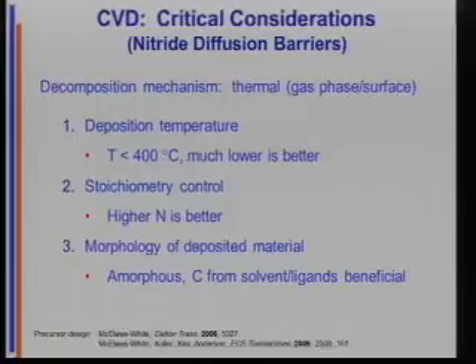So if we're talking about nitride diffusion barriers, the decomposition mechanism under those conditions, it's thermal, right? We're heating the wafer from the bottom, okay? The deposition temperature, oh, for you organometallic chemists, low temperature CVD is 400 C, okay? So I have actually had my industrial and engineering collaborators ask me with a perfectly straight face, can you think of an organometallic molecule that will decompose at 400 C? Got it, okay. However, for reasons which have to do with the processing of chips, lower is better. So you want to minimize the temperature.